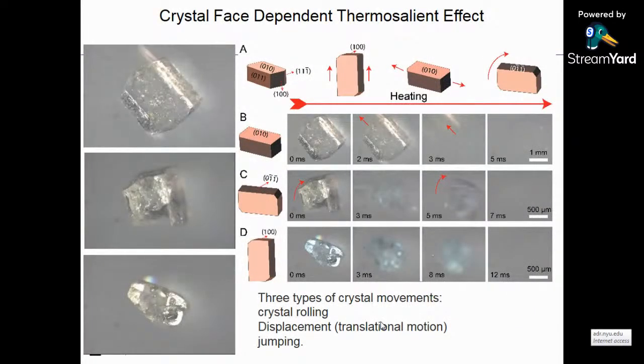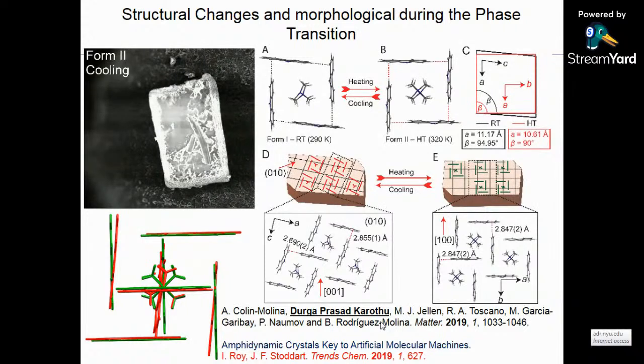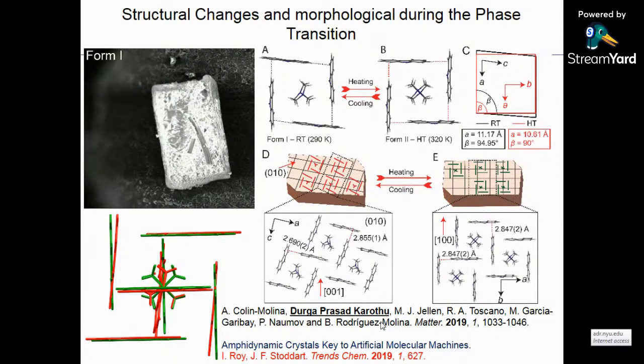And also these crystals are known for their phase specific behavior. That means you can see here the crystals are kept on different phases. So when you keep them on different phases, due to the single crystal three-dimensional structural orientation, they show translational motion, rotational motion, upward motion. For example, you keep them on 0, 1, 0 phase, you can see the movement is like a translational motion, they move forward. When you keep them on different phase, you see upward motion and rotational motion. And we have explained these different kinds of motions by using single crystal X-ray diffraction.